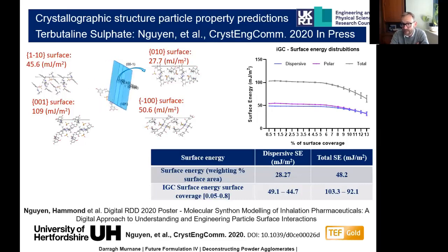And I guess the really interesting thing for us from this work was that it was obvious that our experimental techniques weren't able to probe the high surface area regions of the crystals of drug. It was really only picking out, even at pretty high surface coverages of 12% or so, the very high surface energy regions. And that's quite important to us, because the high surface energy regions are actually a very small proportion of the drug crystals which are being formulated. So it wasn't really giving us a very good understanding of how these materials were going to behave. So again, that's work which we've now just had published in CrystEngComm as our first publication from this project on the crystal modelling work.